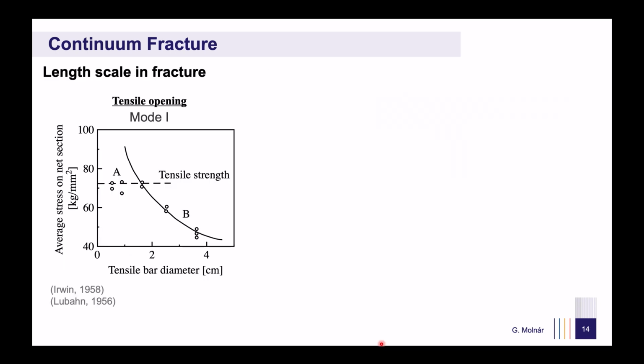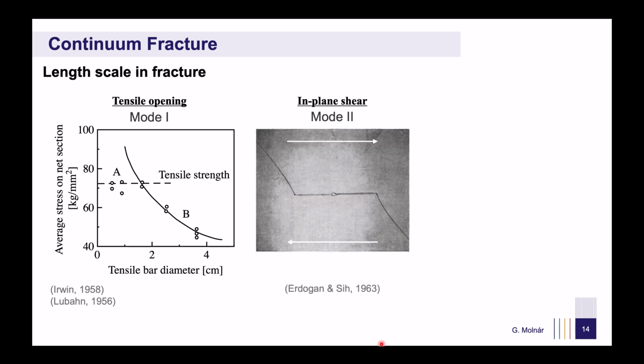In this talk, I will focus on 3 fundamental fracture modes, demonstrating how traditional linear elastic fracture mechanics can be misleading and how different length scales naturally emerge in even the simplest fracture cases. In mode 1 tensile opening, I will show how the initial crack size affects the critical loading. In in-plane shear, I will explain why the crack branches at an angle, depending on the regularization scale, instead of propagating in a self-similar manner as originally assumed by Irwin.